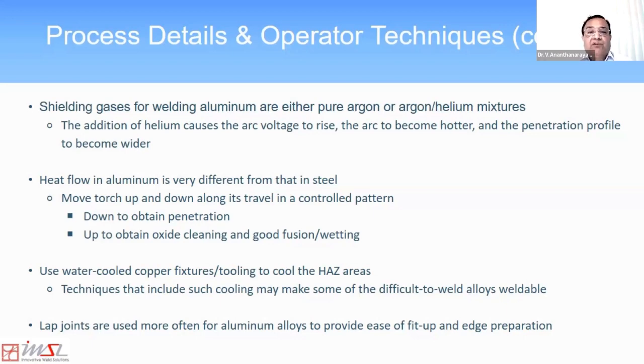And then they keep doing this with a good cycle, and they're all trained and certified to provide good fusion and penetration. And they are checked frequently by sectioning checks and also by bend testing, as you know. Some of the boat manufacturers and other ship manufacturers use water-cooled fixtures to cool the heat-affected zone areas, so they don't become susceptible to the sensitization corrosion that I talked about. So this may make some of the difficult to weld alloys, particularly for marine applications, more weldable. So when you are designing fixtures, please think about this aspect.